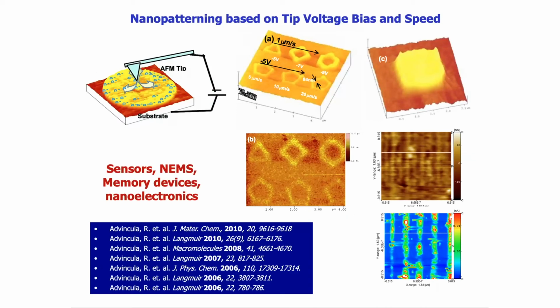Now we are able to transform this into a nanopatterning strategy by using a conducting AFM tip, where the bias voltage can be passed between a conducting substrate and a conducting tip. So this bias voltage actually delivers enough to cause Joule heating or to cause electropolymerization. We can have a negative or a positive voltage bias, which in turn results in an electropolymerization of, let's say, that PVK monomer that I showed earlier.